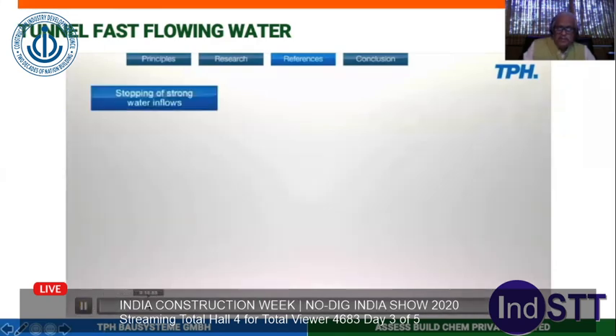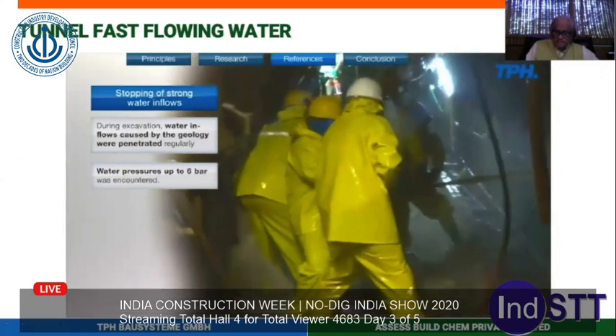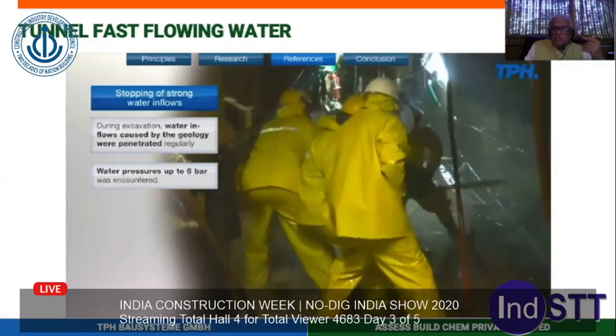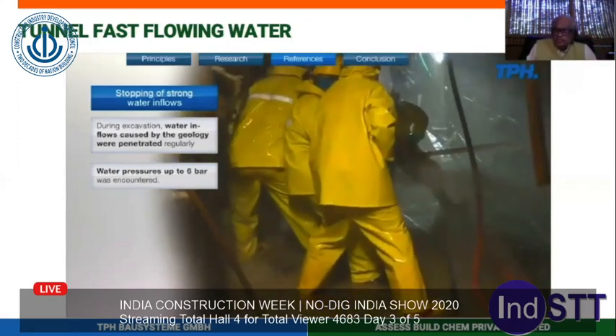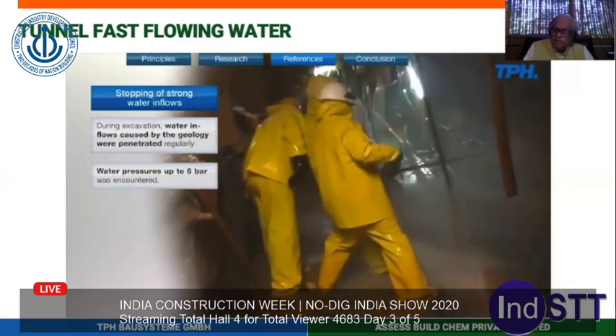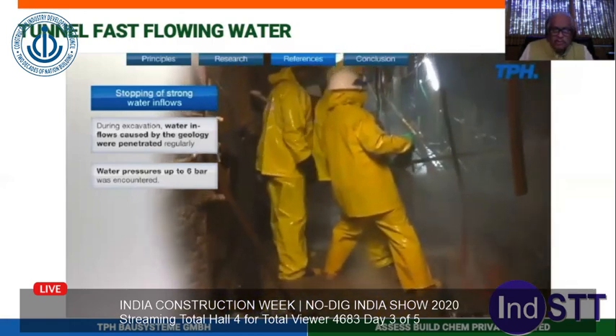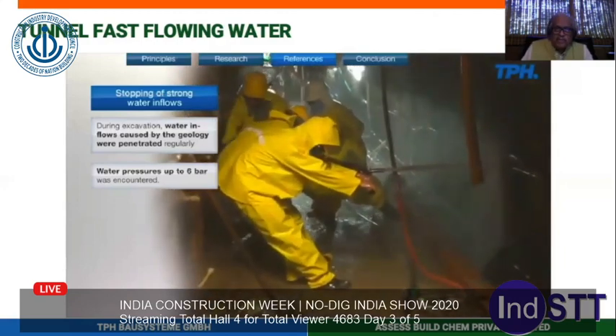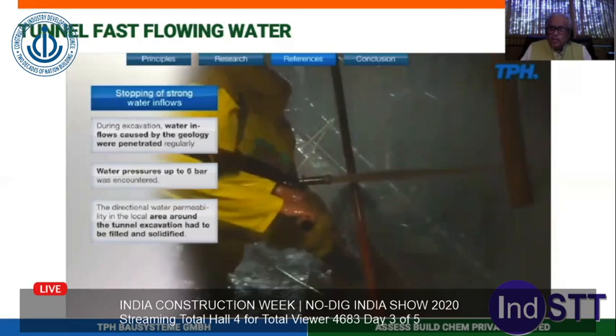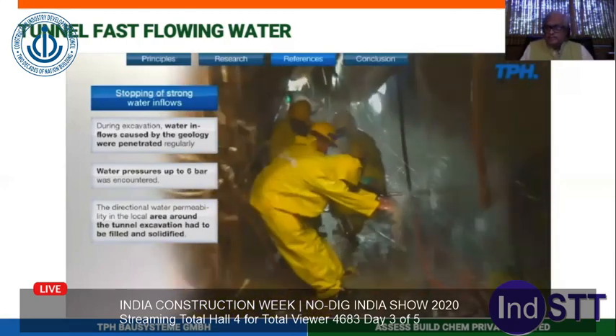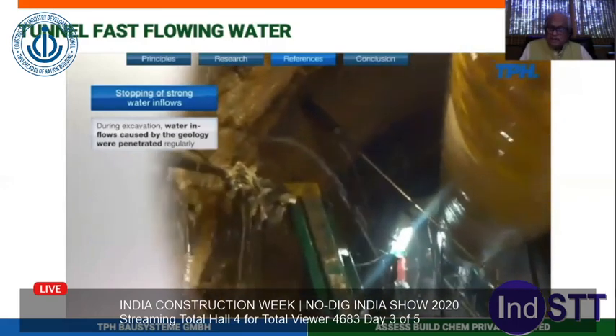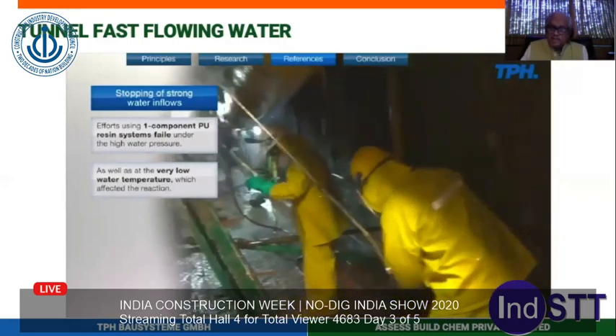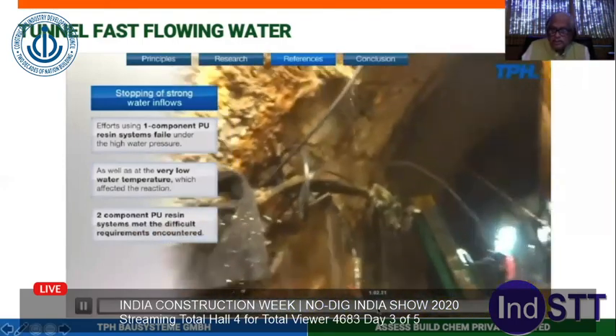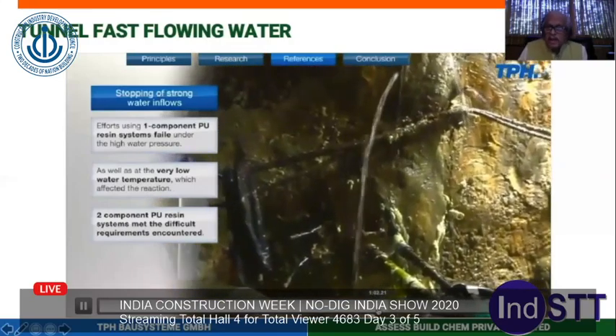In structures like tunnels, the water will be gushing. With this type of water gushing, which is more than 6 bars, you can imagine yourself if you start injecting this with cement or cementitious materials or even one component foams. The pressure of the water which is coming is 6 bars. You will not be able to stop it with one component foam, even temporarily. Let us not talk about permanent stopping, but even temporarily. So primarily, you will have to go in for two component injections, because two component injections have controlled reactions. They are a little bit harder compared to one component.